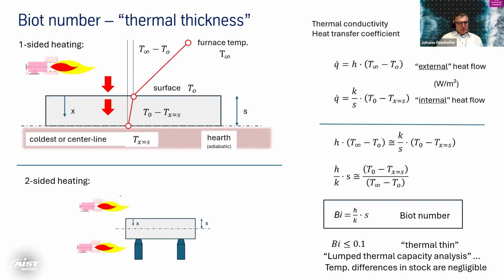What is the Biot number? That describes the thermal thickness of a slab, for example. So what does that mean? We have an external heat flow. This is the heat carried from the outside to the slab. This is the heat transfer coefficient times the furnace temperature, T infinite, minus the surface temperature of the slab. And we have the inner temperature, surface to the center, at x is S. This is the thickness of the slab, so to say.